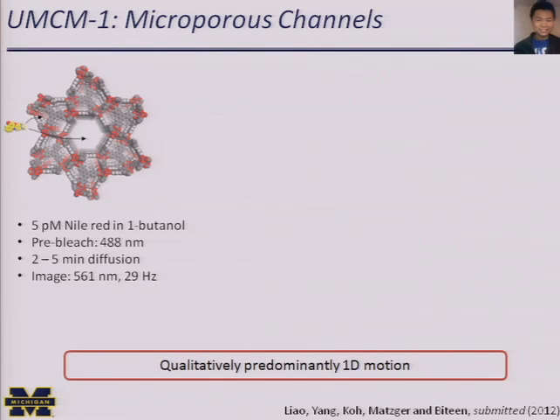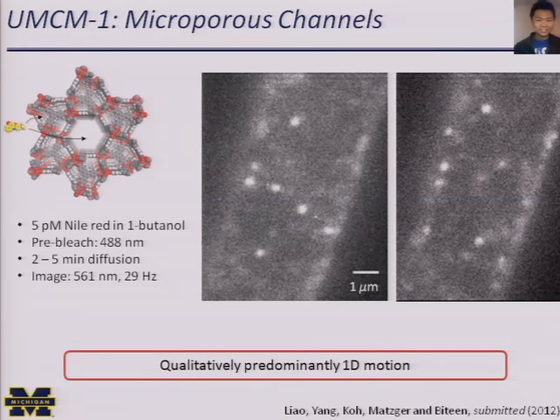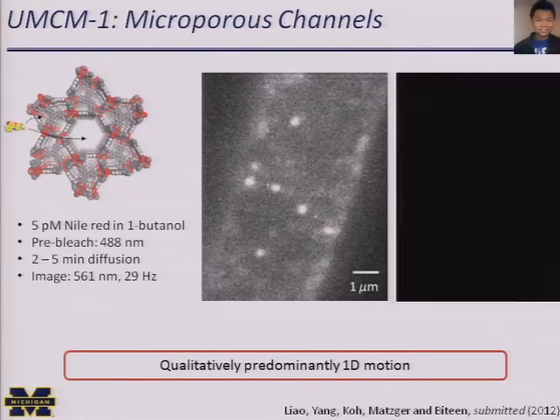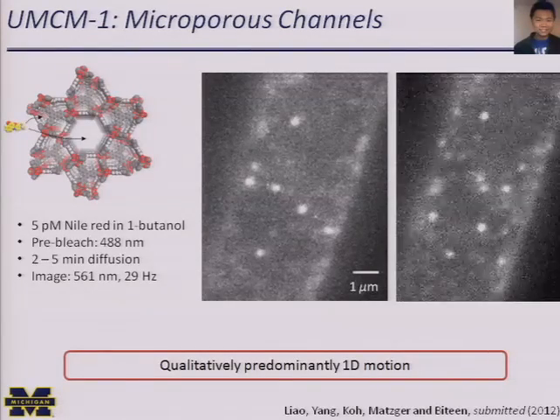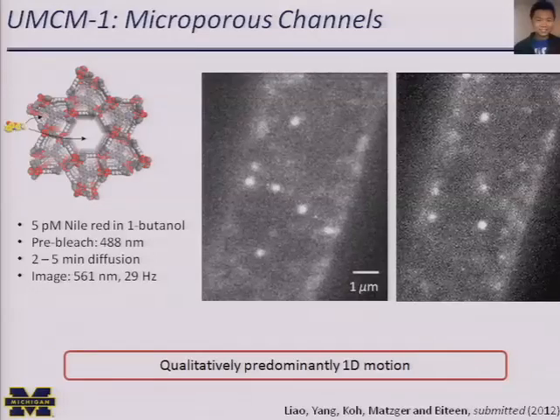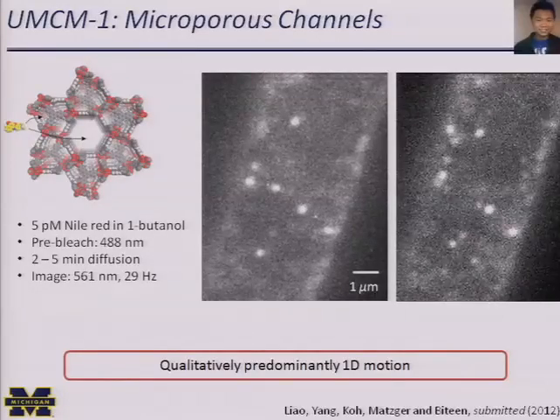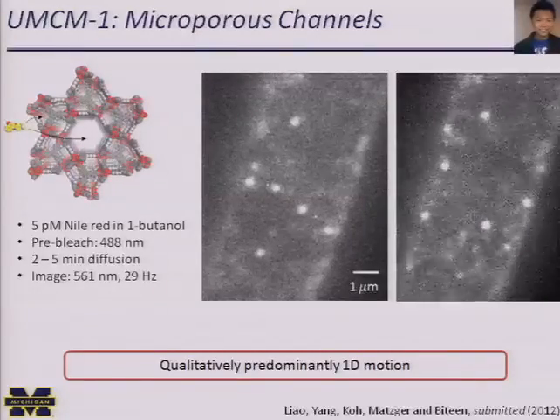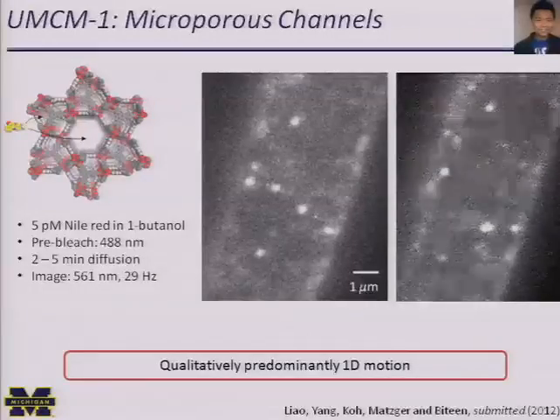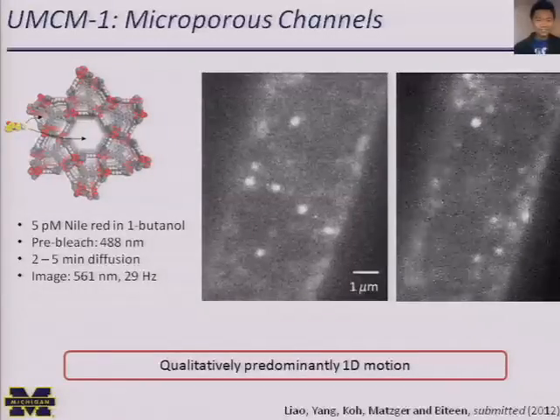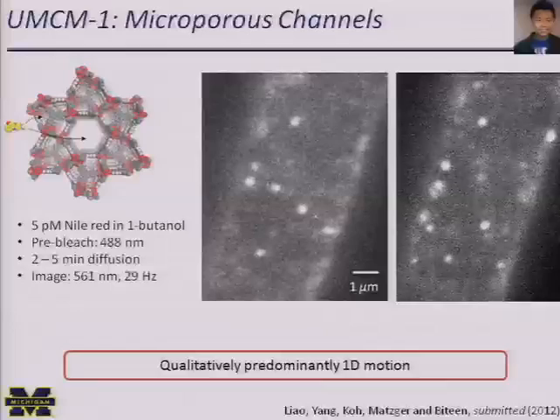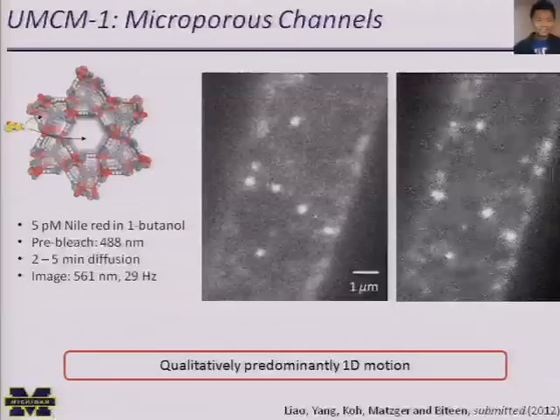And then the imaging is done at 561 nanometers and 29 hertz. And so when we look at these crystals, they form these nice long needles due to their linear channels. And we can image diffusion in the crystals. And here we start to see the molecules moving back and forth along. And so we see predominantly 1D motion with a few other subtleties.